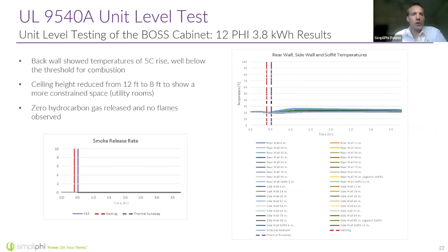The back walls of the enclosures of the BOSS 12 cabinet show a 5-degree temperature rise. The ceiling height was reduced to 8 feet, like I mentioned, to demonstrate a more constrained space, such as is typical in homes, typically 8-foot ceilings. We had 0 hydrocarbon gas released and no flames observed. Remember, outside the cabinet, we're not seeing any problems, really.